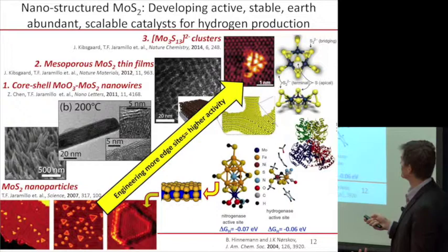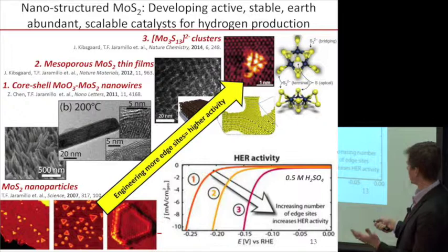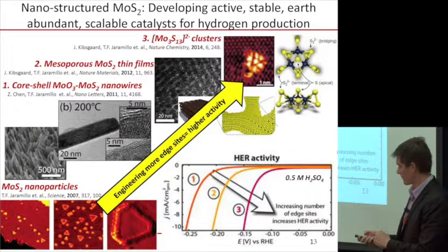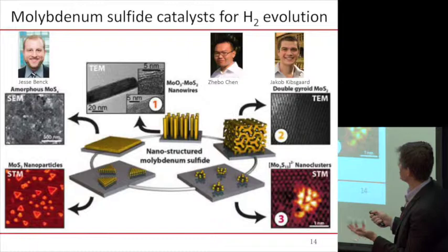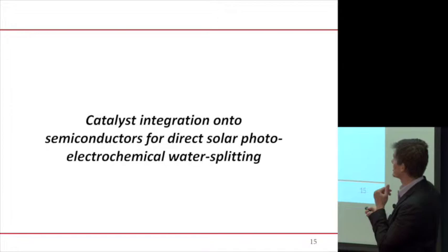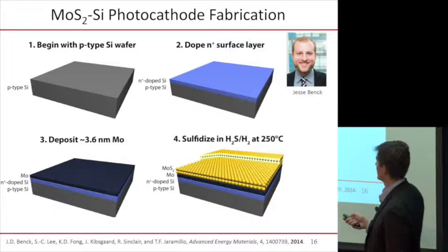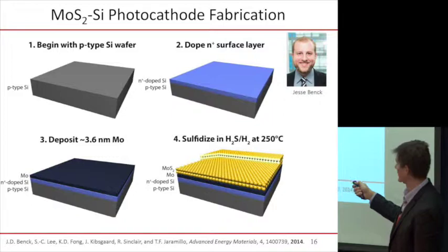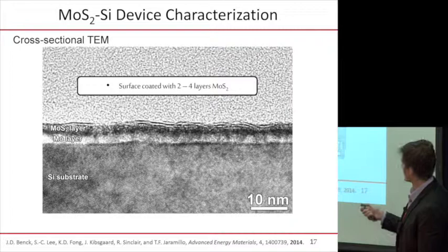You can see from this current versus voltage plot that we're just marching our way from left to right, getting closer and closer to zero. Once we started making these types of catalysts, we asked ourselves, what do we want to do with them? The answer is to start integrating these onto semiconductors for direct solar photoelectrochemical water splitting. So my student Jesse went to the clean room here at Stanford and started making himself a PN junction solar cell of silicon, then layered a little bit of molybdenum and made a molybdenum sulfide on top. This is what it looks like from a cross-section transmission electron microscopy image. We can zoom in a little bit.